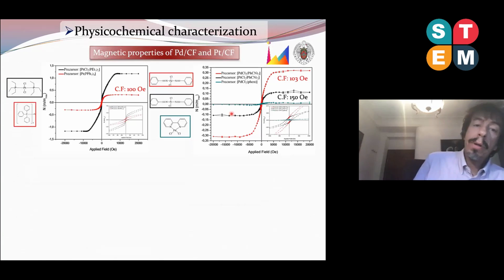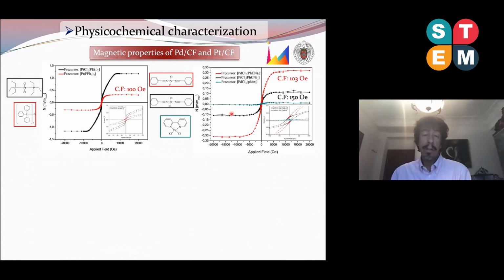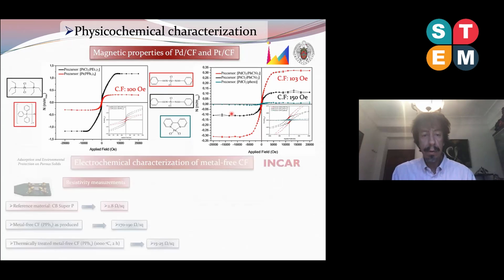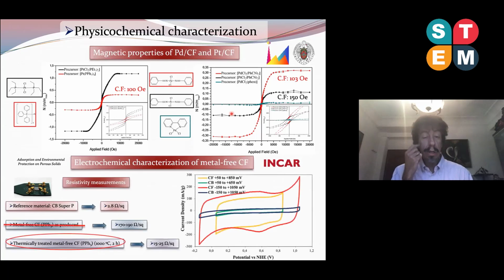We also performed some other kind of physicochemical characterization studies, mainly on palladium and platinum containing carbon foams. And we observed, these results are really preliminary, so we have to be cautious about them, this kind of ferromagnetic behavior. Also, we did some electrochemical characterization of metal-free carbon foams, and we observed that when thermally annealed, we can get an increase in electrical conductivity and in capacitance of these materials.